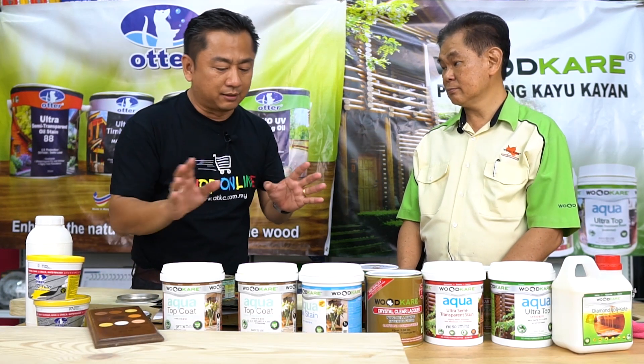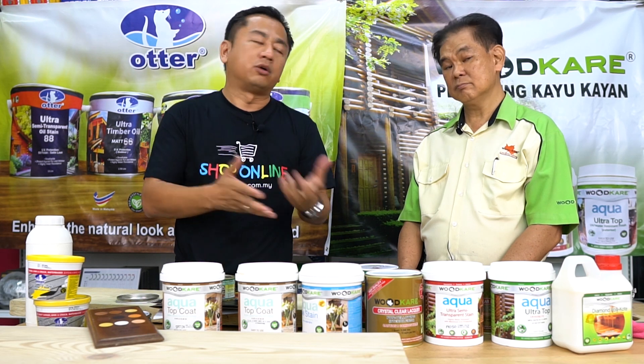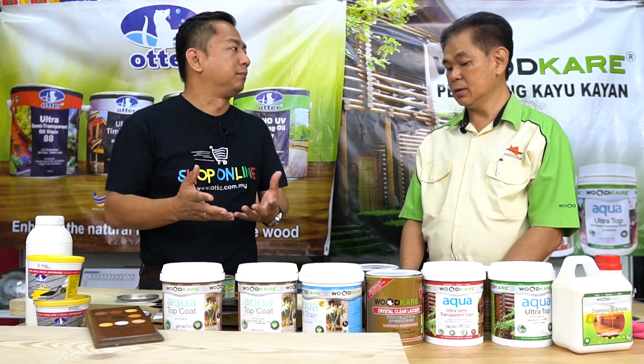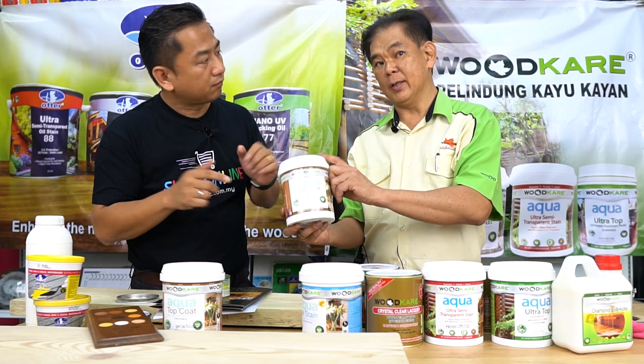My question is: once I stain everything and it looks nice, I always have a problem choosing the finishes — whether to use a glossy finish, semi-matte, or matte finish. Can you let us know about Wood Care's offerings? This gel stain is dry in two hours. After two hours, you can apply what's called Aqua Top Coat. Aqua Top Coat is a water-based acrylic — very friendly to use, no odor, non-toxic. We have a sealer; normally you apply one to two coats of sealer, then after two hours drying you can apply a gloss or matte finishing on top.